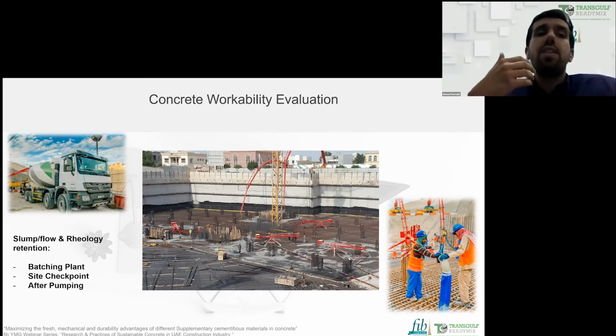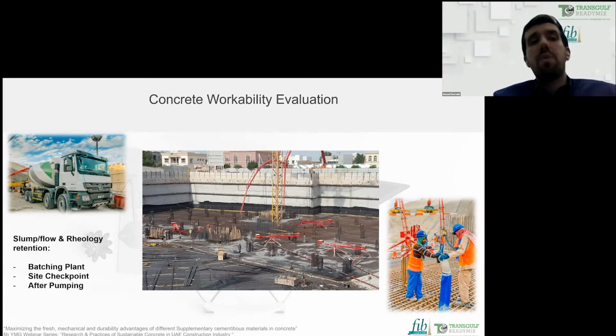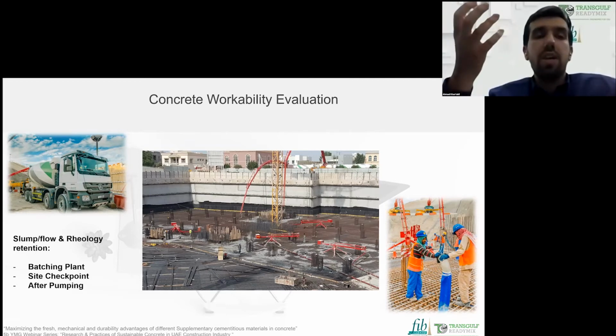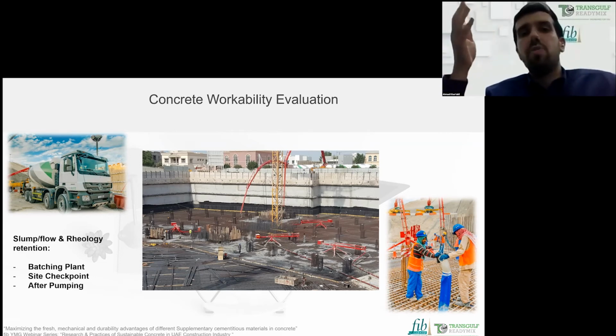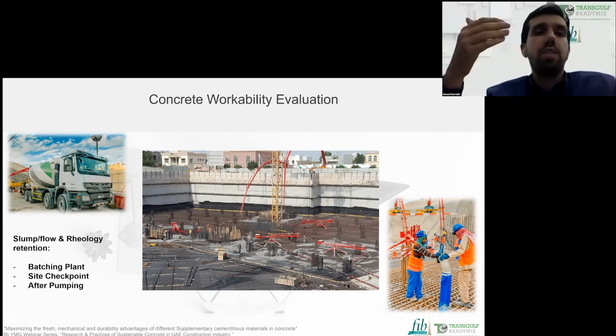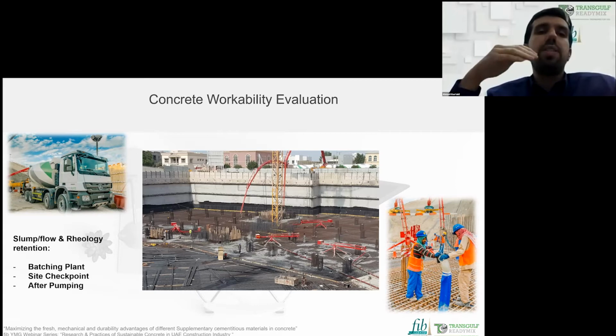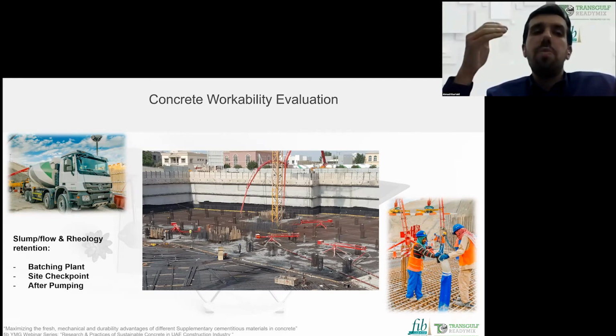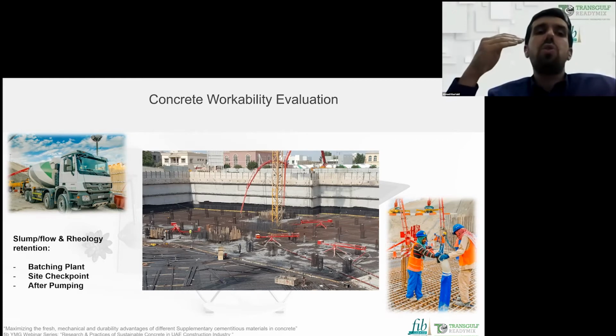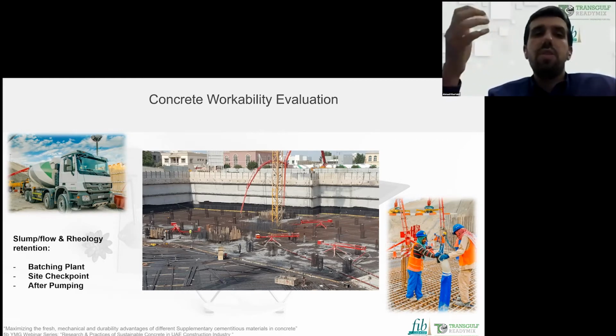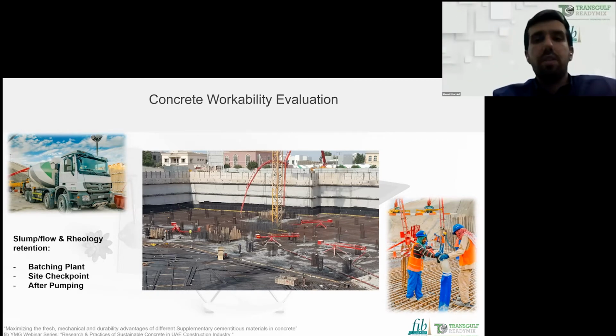And the slump that was measured before batching might differ after batching, especially if you're using one type of supplementary cementitious material like GGBS, which is always advised in the industry. Even in the circular, they allow for higher slump, because replacing Portland cement with GGBS at high percentages makes the concrete more viscous.